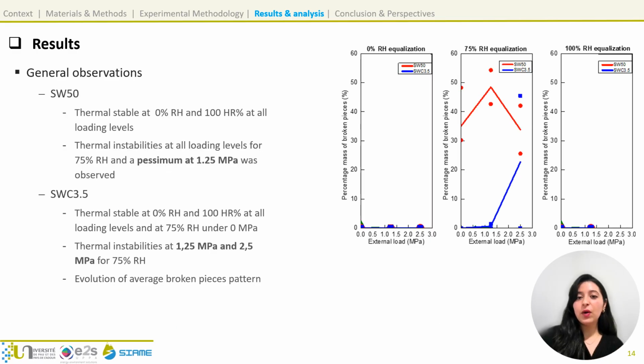This graph here highlights how load intensity affects spalling in the bricks and shows the percentage of broken pieces. For SW50, the unstabilized brick, stability was maintained at 0 and 100% relative humidity, but under 75%, instabilities occurred at all loads, with a maximum effect at 1.25 megapascals. For SWC 3.5, the cement-stabilized brick, stability was maintained at 0 and 100% relative humidity for all loads, and also at 75% relative humidity under zero load. However, at higher loads, 1.25 and 2.5 megapascals, instabilities were observed.